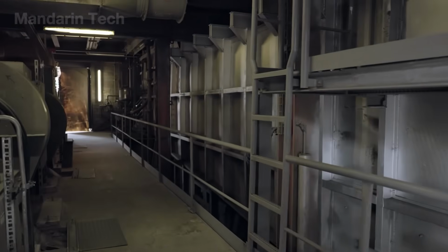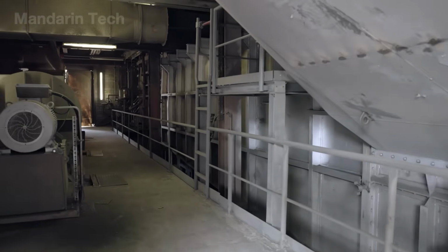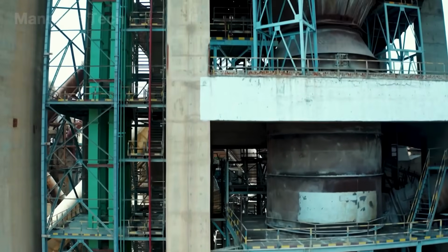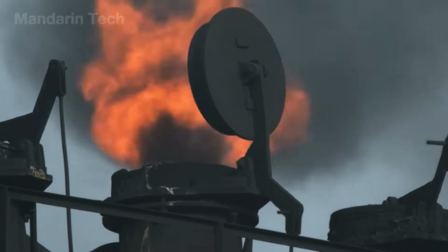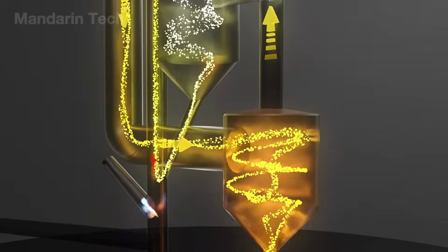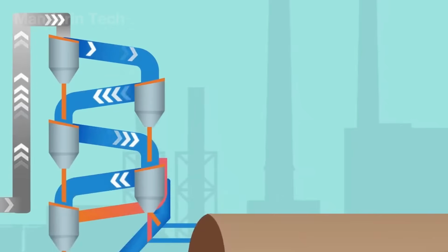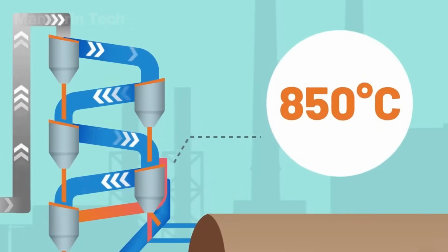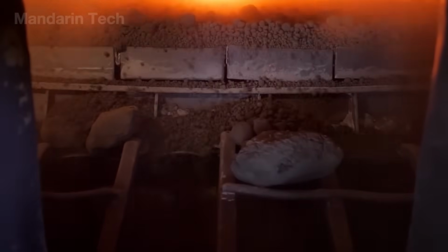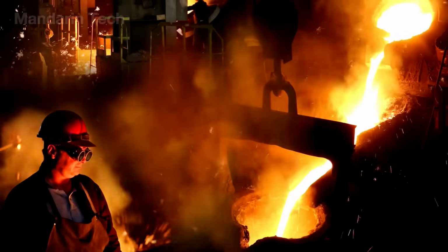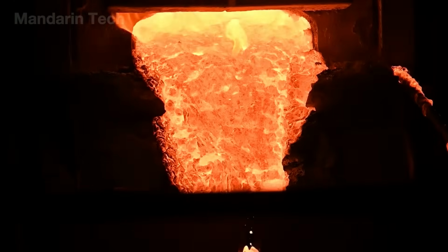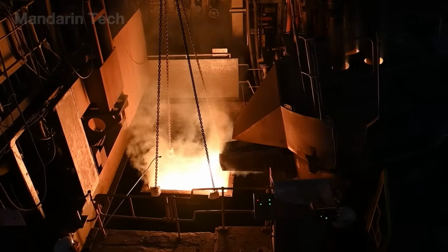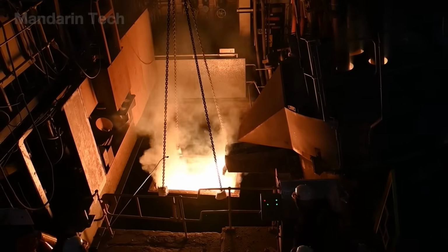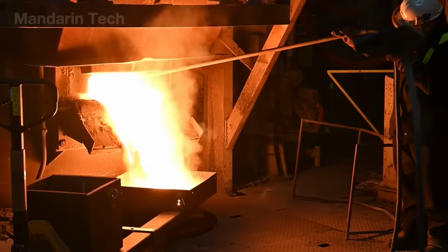stage. Heat from the hot gas flow spreads through the preheater tower, but the raw material must follow its own path before entering the harshest stage, the rotary kiln. From the top of the tower, the limestone clay mix drops through tall cyclone chambers, spiraling with the rising hot air. Each cyclone works like a natural heater, raising the temperature of every particle to around 850 degrees Celsius within seconds. In the calciner, the heart of the tower, carbonates break down almost completely, turning the raw meal into minerals ready for high-temperature reactions. This multi-stage structure operates like a vertical river of material, weaving through steel chambers and absorbing energy from the burners below.